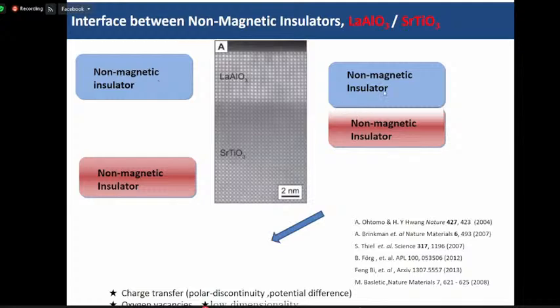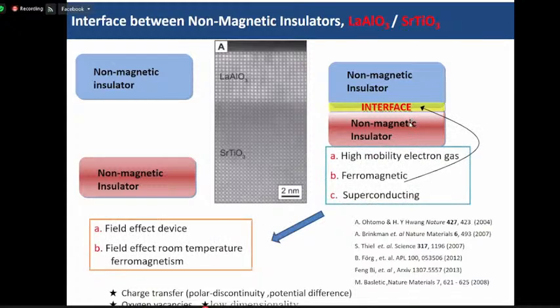Then they put them together. What happened? Because of the interface, they show a high mobility electron gas at the interface, and then some ferromagnetism and superconductivity. It's so amazing because both of them are non-magnetic insulators, but they show a high mobility electron gas, ferromagnetism, and superconductivity. So many researchers try to use field effect devices and field effect room temperature ferromagnetism using these materials, just using the interface.